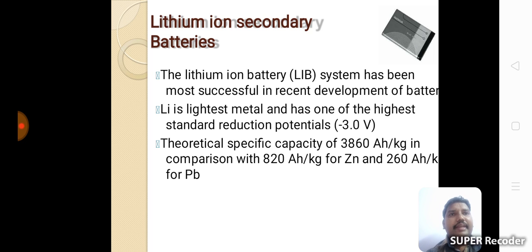The lithium ion battery system has been the most successful in recent development of batteries. Lithium is the lightest metal and has one of the highest standard reduction potentials, that is minus 3.0 volts. Its theoretical specific capacity is 3860 ampere hours per kg, in comparison with 820 ampere hours per kg for Zn and 260 ampere hours per kg for lead.